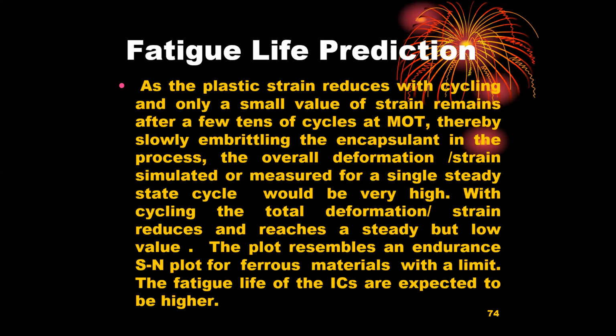Thank you so much. As the plastic strain reduces with cycling and only a small value of strain remains after a few tens of cycles at MOT, thereby slowly embrittling the encapsulant in the process, the overall deformation or strain, which is simulated or measured for a single steady state cycle, will be very high. With cycling, the total deformation or strain reduces and reaches a steady but low value.